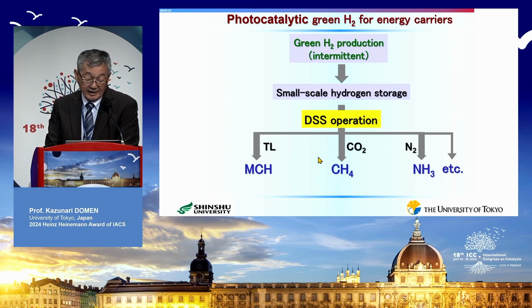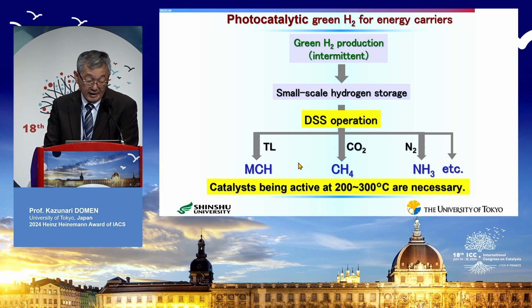To achieve such a reaction, we need a catalyst which is not a photocatalyst, but a thermal catalyst, which can be active at 200 to 300 degrees C. And actually, in the case of MCH and methane, such a practical catalyst already exists. In the case of ammonia, this is a little bit challenging. And then here, let me first discuss the methane formation.